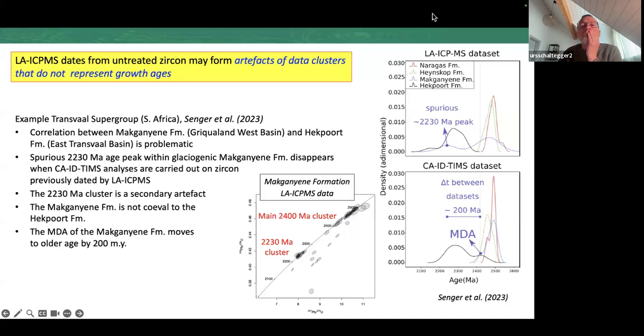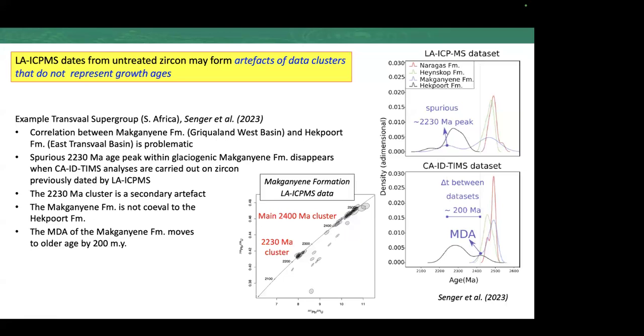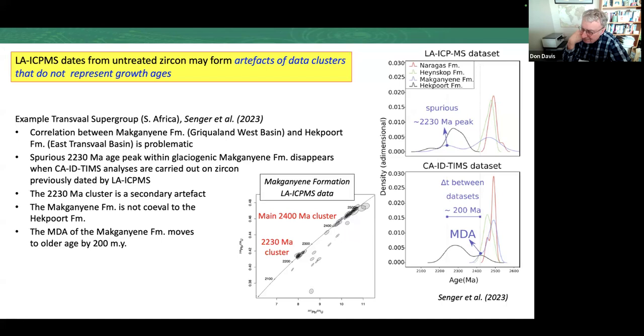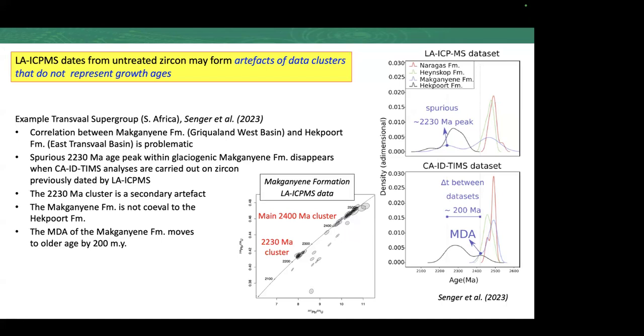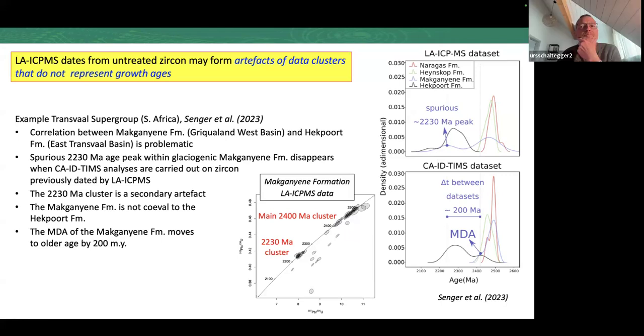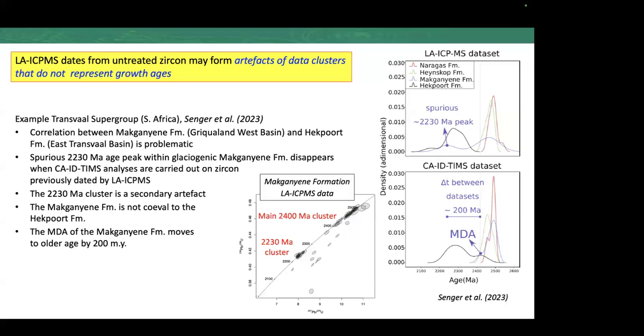And then another thing, based on your previous input, we do control for fractionation factors throughout the entire session, both 206/207 and 206/238. And for each analysis, we do apply this semi-linear correction. And the length of this heavily depends, as you pointed out, on the downhole fractionation issue. The longer you ablate, the worse it gets, right? So one way of circumventing this issue is also to ablate for a short amount of time, so that we never get a pit that is too deep.